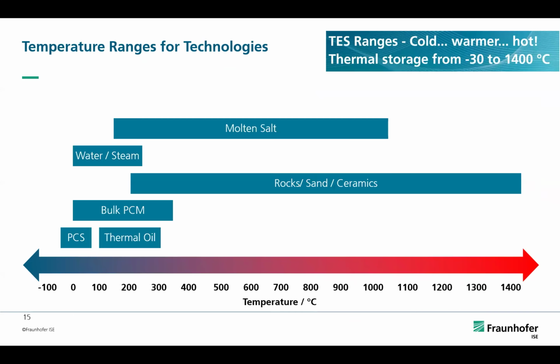Exactly. So wrapping up the temperature ranges, once again, we were coming from the molten salt systems. Molten salt itself, for the LoCoMoSa project, we look into temperatures between 290 to 550 degrees, but depending on the salt mixture, we can also go to lower temperatures or to higher temperatures. The higher the temperature, the more corrosive the salt, the more problematic, I would summarize. Lower temperatures is somehow possible, but then we are also in direct comparison to water-based systems, which are cheaper. So that's also a difficult business case.